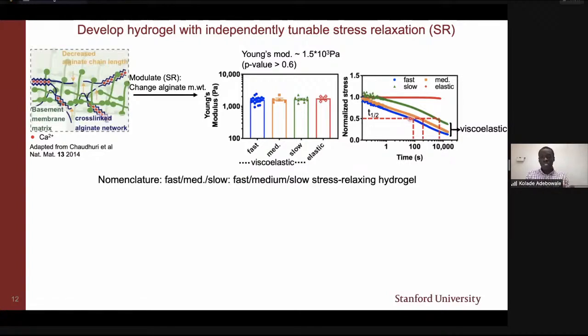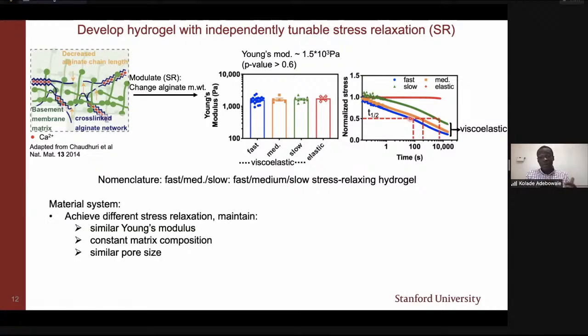So to establish some nomenclature for this part of the talk, whenever you see fast on a graph, that refers to fast stress relaxant hydrogel. In any case, we like this material system because it allows us to achieve different substrate stress relaxation while maintaining similar Young's modulus, constant matrix composition, and similar pore size. This is important because later on, if we observe any differences in cell migration, we can attribute those differences to differences in substrate stress relaxation.